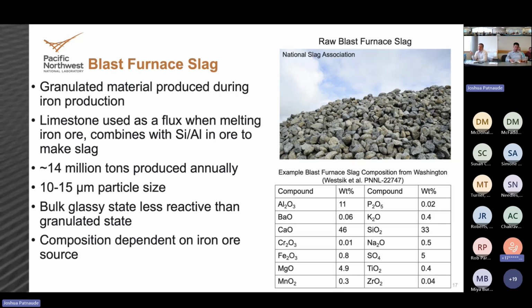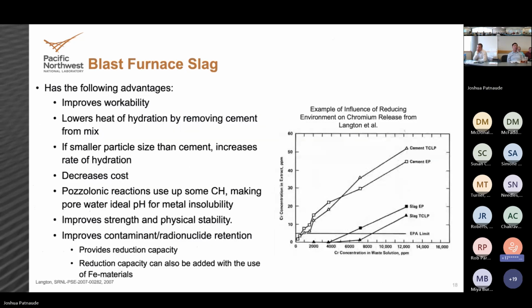You take that glass, you grind it down, it becomes reactive. It's usually a very fine particle size, it's about 10 microns. And when you grind it up, you get higher surface area, it becomes more reactive. The composition of it is dependent on what your iron source was, but a lot of iron sources come from the production of, or the original ore is pyrite, which contains sulfur, and the sulfur is a key component for us in waste immobilization. Let's go to the next slide.